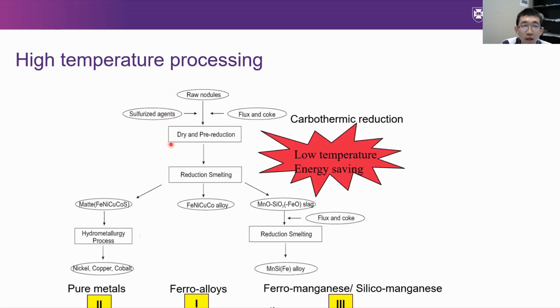Also in the mixing stage, we can mix in sulfide agents to produce the matte. So the purpose is we just optimize the slag and then the alloy grade, and try to achieve a low temperature operation and save the energy in this carbothermal reduction.